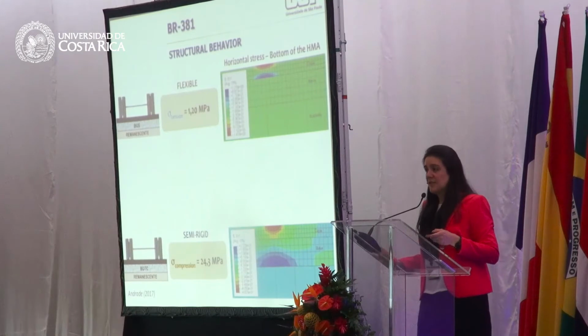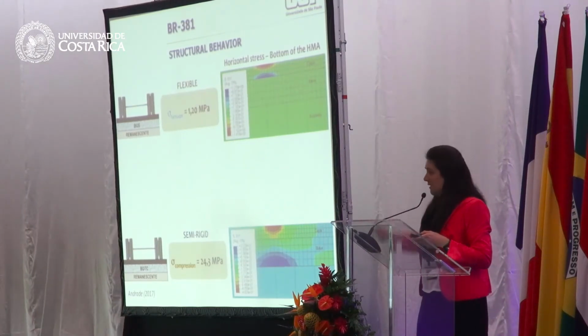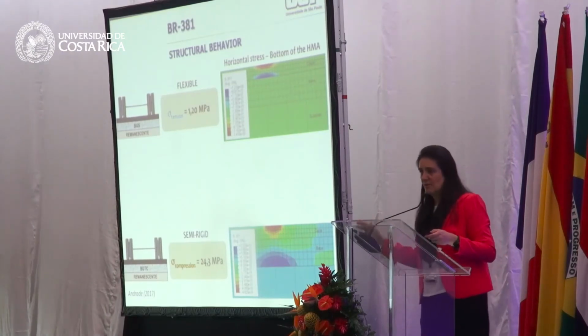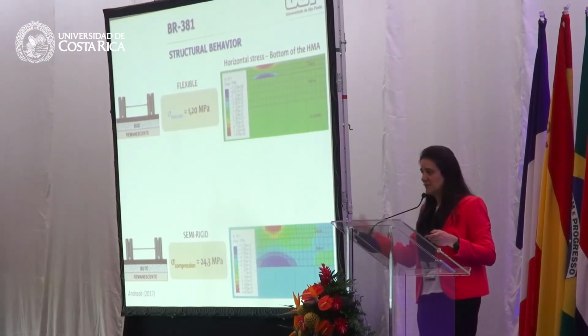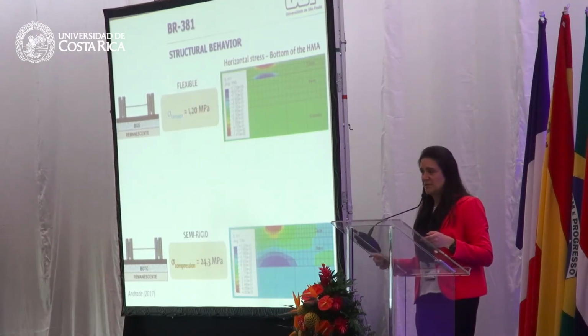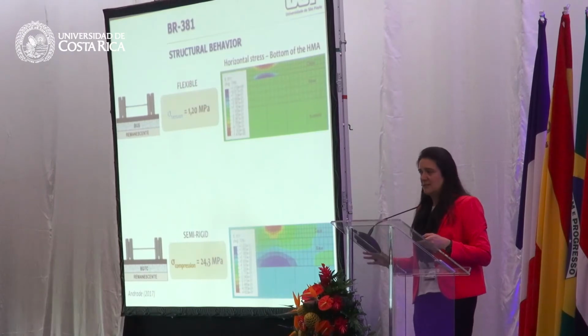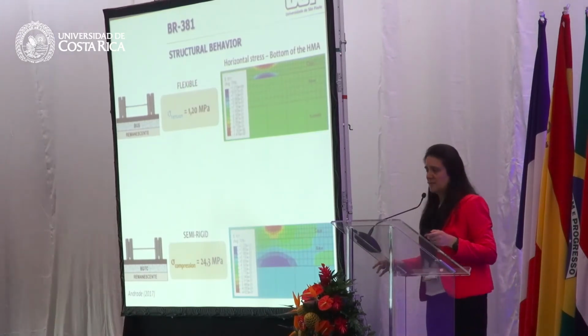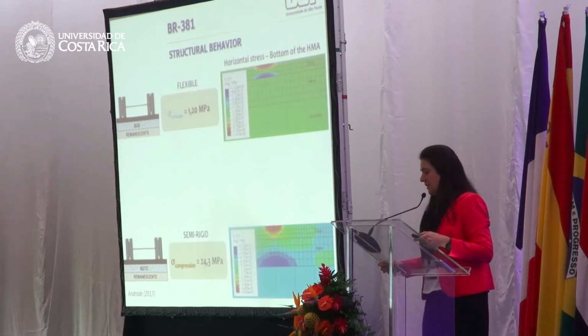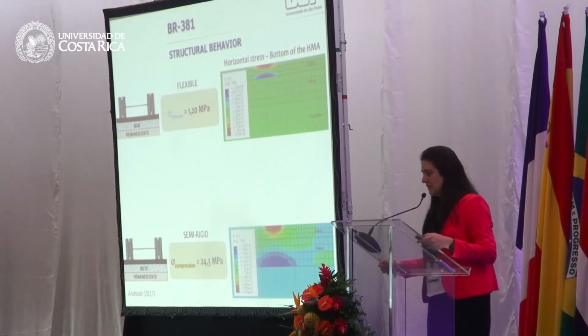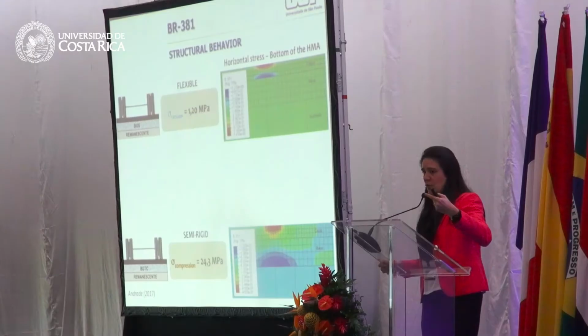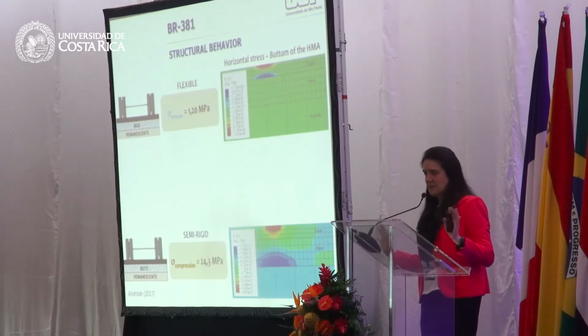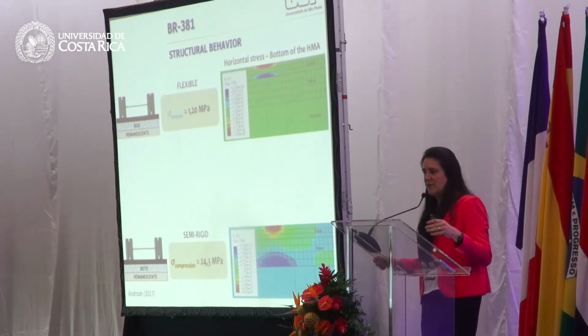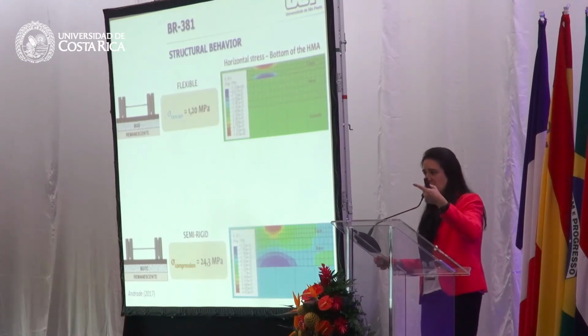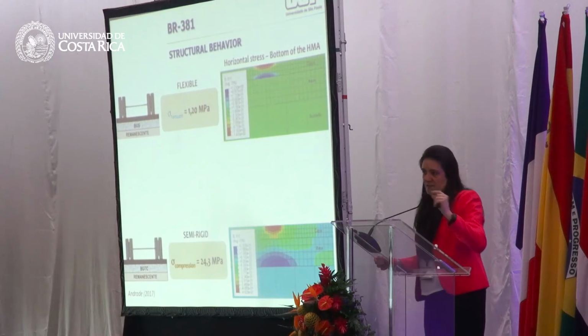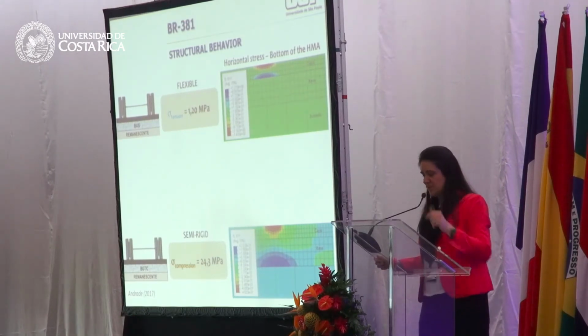And these two mixtures are in the field with two other structures. One, completely flexible. This one is gone already, by the way. After less than 2 years, we had 70% of the surface cracked. So with heavy traffic, the flexible structure didn't work there. Here we are looking at the stresses at the bottom of the HMA. If we compare the flexible structure with the semi-rigid structure, everything is okay. If I have a cement-treated base, my HMA will not be under tension. The bottom part of the HMA is going to be in compression.